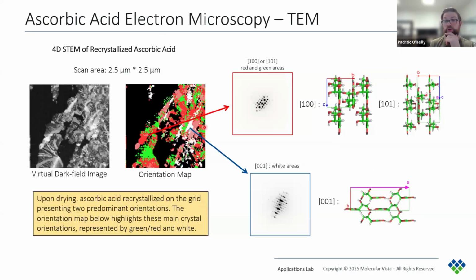So in this example, we show how PiFM can be carried out on the same samples used for TEM. Ascorbic acid is dropped on a TEM grid and recrystallizes. 4D STEM shows that the recrystallization results mostly in two prominent orientations. So the results shown on this slide are a general example. The crystals shown in the following slides are part of an ongoing study.